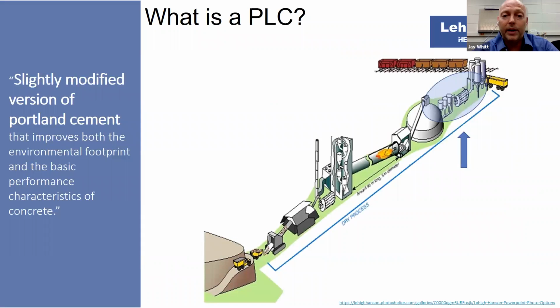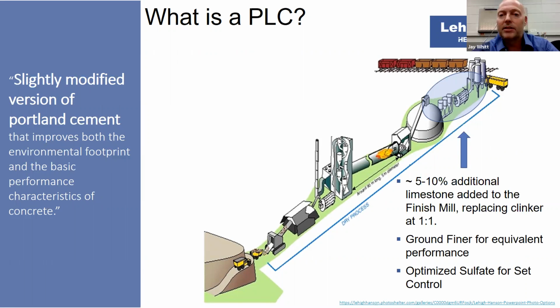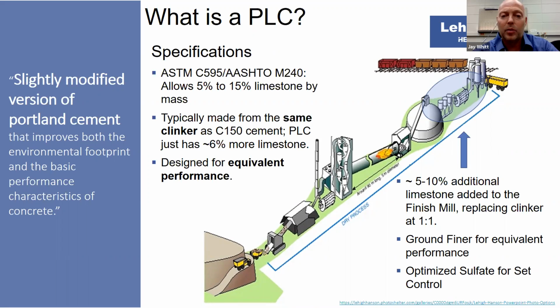So really, what is PLC, Portland limestone cement? You may hear it that way, or you may hear it as a type 1L. It's a slightly modified version of our Portland cement. What do I mean by slightly modified? Well, we're actually adding increased limestone percentage, about 5 to 10% in there. We're grinding it a little bit finer, but we're putting this into the process at the finish mills in the cement manufacturer. We're optimizing sulfate for set, and we're ready to go to look at the specifications.